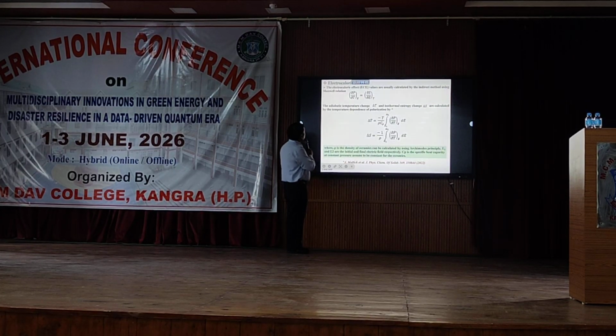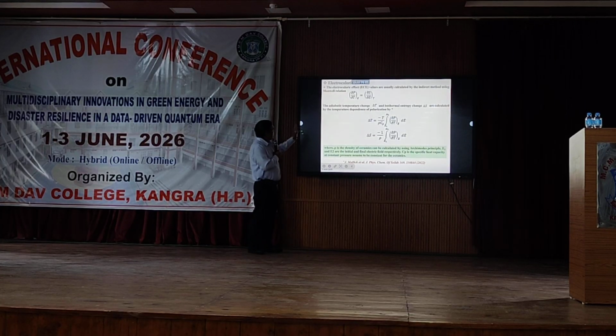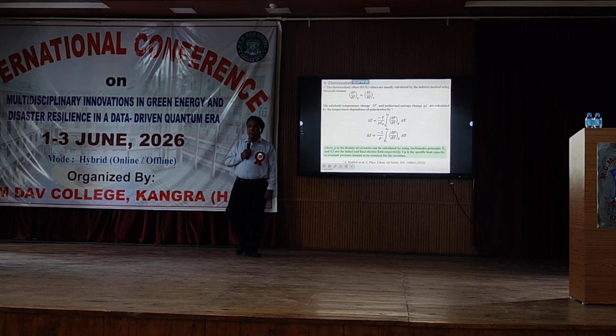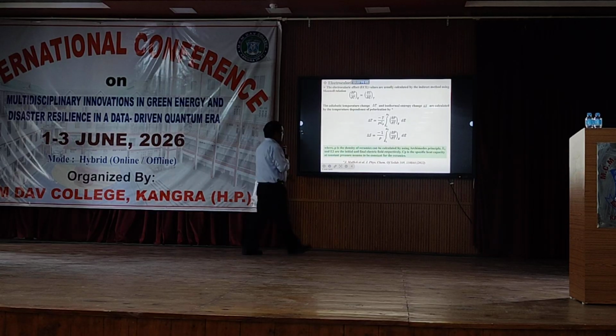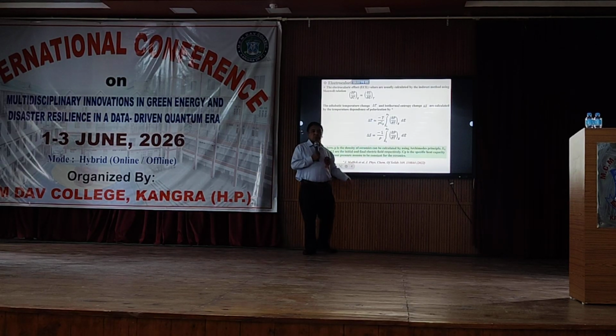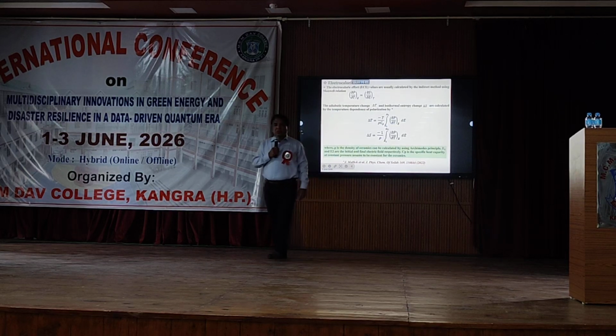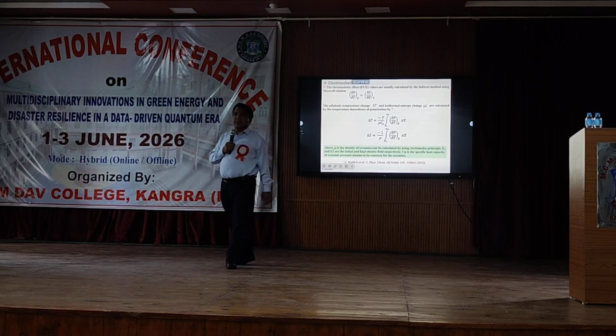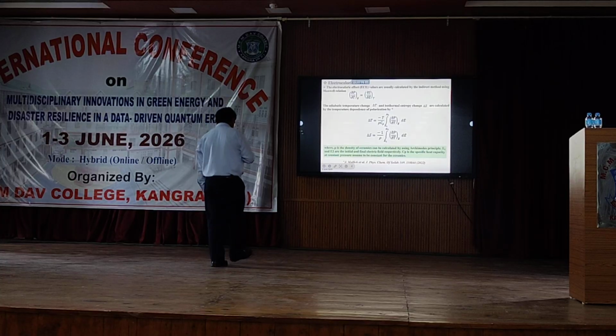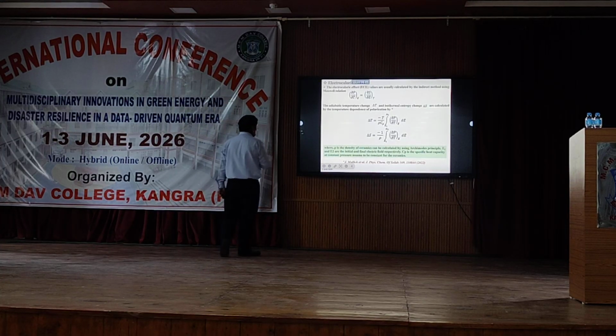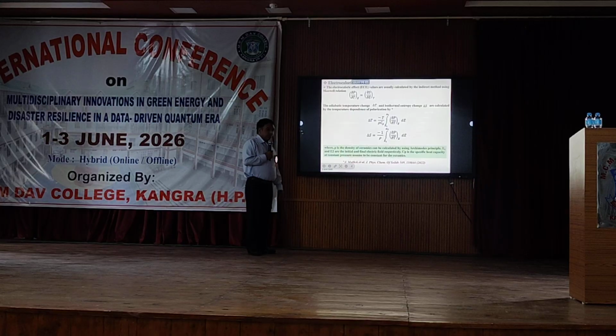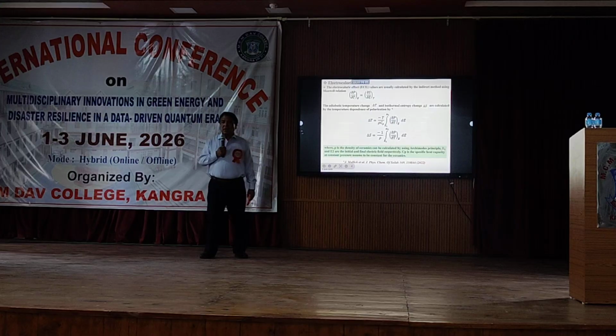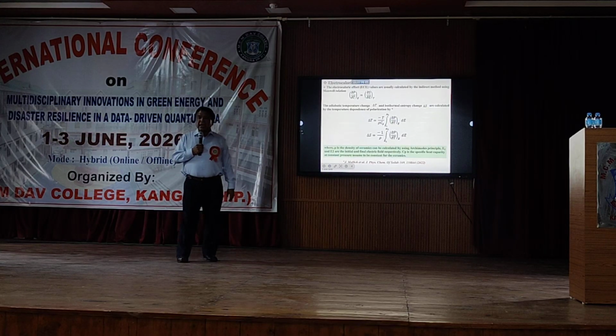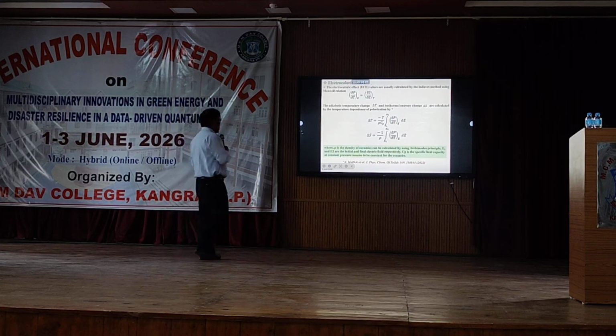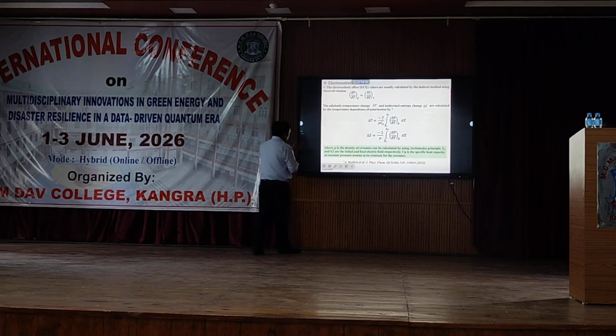So how we calculate this electrocaloric effect using Maxwell relation, and after doing some analysis, these two are the formula used to calculate isothermal entropy change and adiabatic temperature change, where rho is the density of the material and Cp is the specific heat at constant pressure, and one can measure the polarization, where hysteresis is low, at different temperature and calculate both these factors effectively using these two formula.